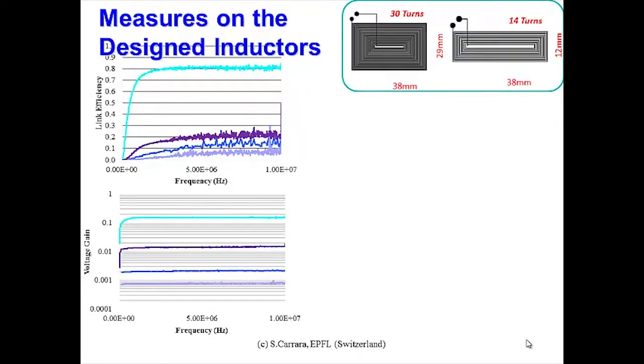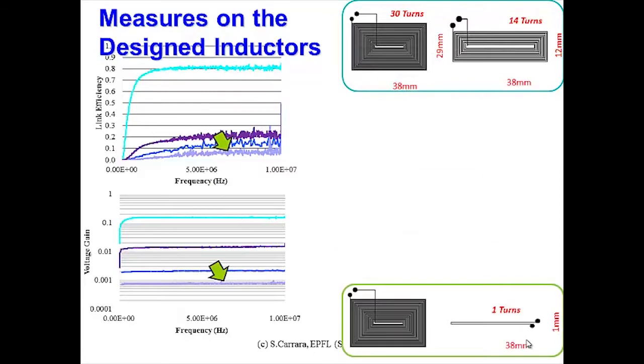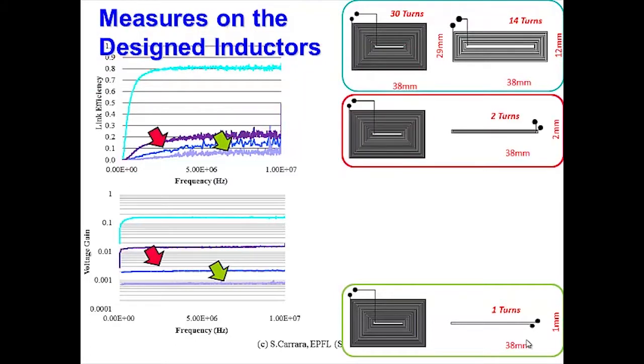The problem is that, of course, in all the published papers we have reasonable size also for the receiving coils. What we have immediately observed is that if we reduce the lateral side of our receiving coil, our link efficiency and our voltage gain drop to unbelievably low values. So the only chance we have to increase the link efficiency as well as the voltage gain is to increase the number of turns, but this forces us to lose the tiny lateral size of our device.